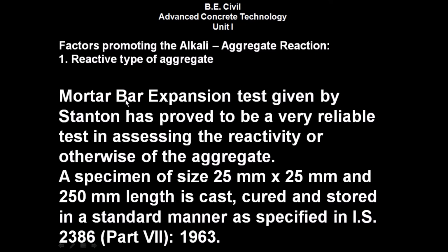Mortar bar expansion test given by Stanton has proved to be a very reliable test in assessing the reactivity or otherwise of the aggregate. So a specimen of size 25 mm by 25 mm in cross section and 250 mm in length is cast. It is cured and stored in a standard manner as specified in the Indian Standard IS 2386 Part 7, 1963.